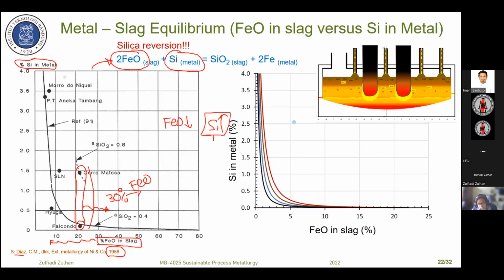The silicon content sometimes has an advantage for the AOD converter. There's a trend to process the NPI directly in the AOD converter, where the molten NPI will be charged directly into the AOD converter. In that case, we can add solid ferrochromium into the AOD converter. We do not need any EAF for the melting of the ferrochromium or the other kind of material for stainless steel making. We just charge the molten NPI into the AOD and then solid ferrochromium, and then for the first time, for sure, we blow in oxygen.